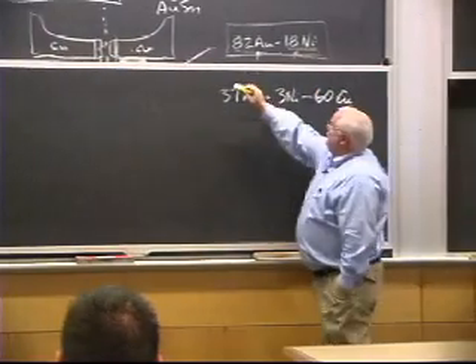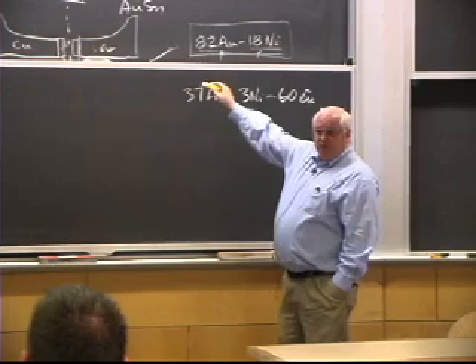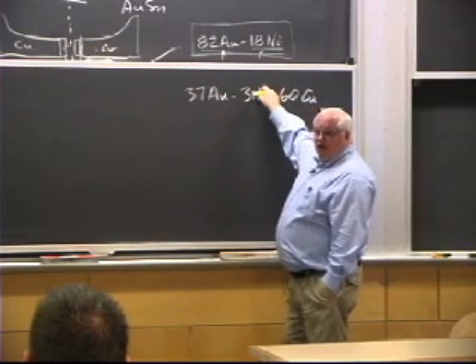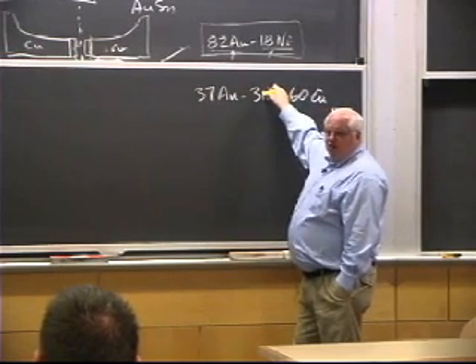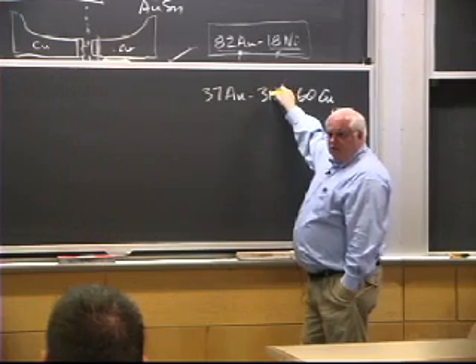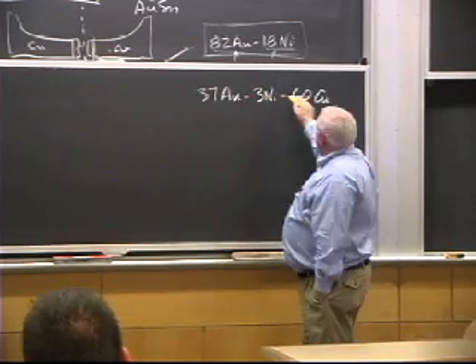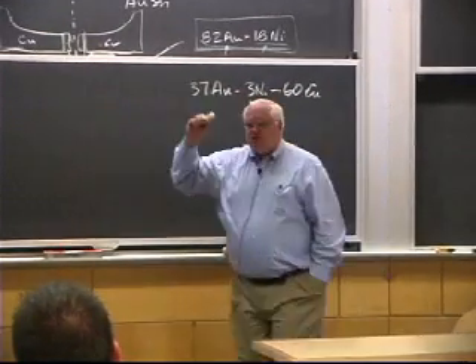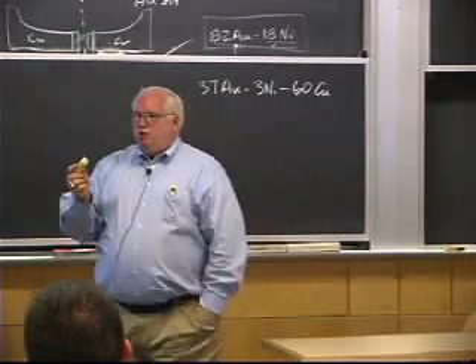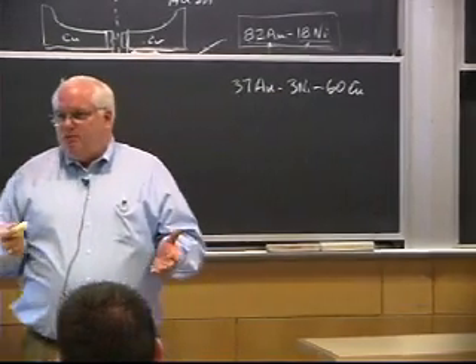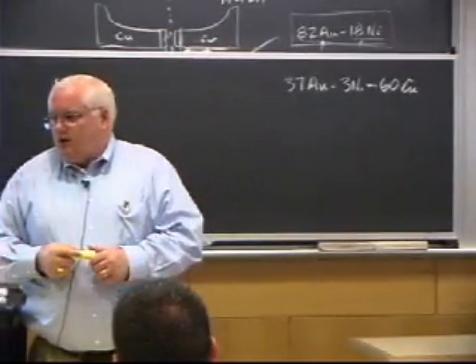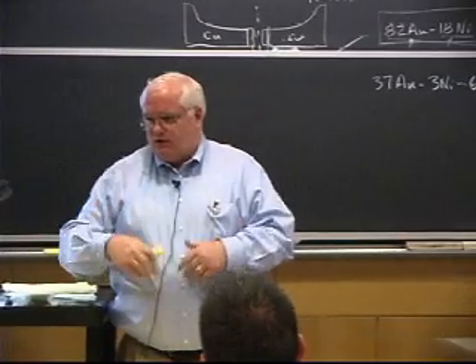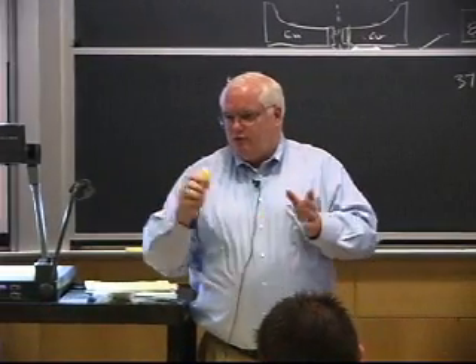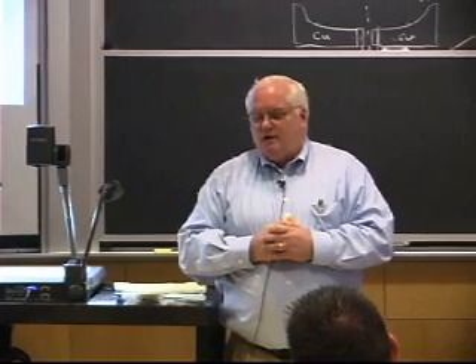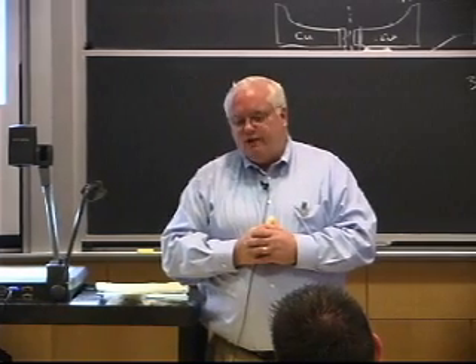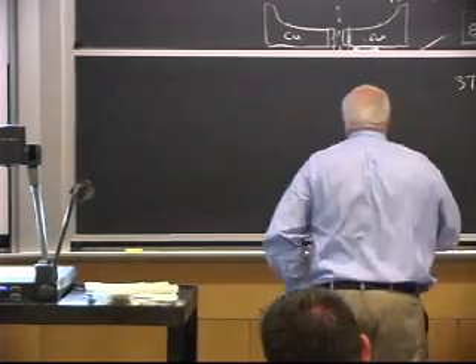It turns out they did get rid of the nickel-3 tin intermetallic, because lower nickel lowers the activity of the tin, so you didn't form the nickel-3 tin intermetallic. But the gold just diffused into the copper as the melting point depressant, and they ended up forming a TLP bond. They didn't know they had stumbled on it. I ended up writing a letter explaining all this, and the Navy internal person at the site signed off on it. Another story that has to do with TLP was